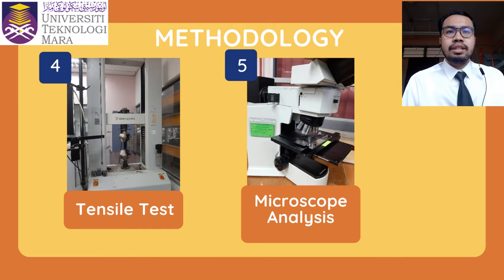While being tested, the material will be monitored and measured by the extensometer. To begin the tensile stress test, carefully separate the tensile clamps at constant speed. Testing was done at a constant head speed of 2 mm per minute. During the tensile test, the sample will generally break in less than 5 minutes.